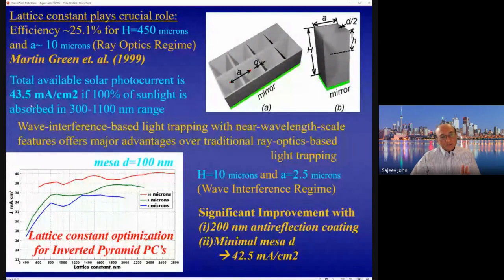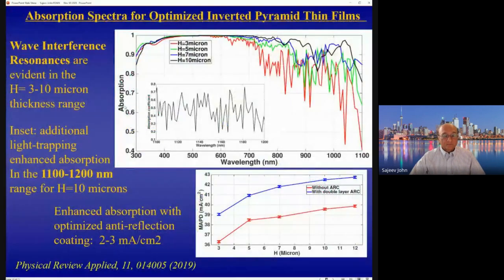And that should be compared with the total available sunlight in the 300 to 1100 nanometer range, which is 43.5 milliamps per square centimeter. And we find that a further improvement is possible if one adds an anti-reflection coating on top of this, say silicon dioxide, and one makes the mesa, this parameter d, as small as possible, maybe as little as near 0. This increases that photocurrent density up to 42.5 milliamps. So with this very thin structure of only 10 microns in thickness, we can absorb about 98% of the sunlight within this broad range of wavelengths, despite the very weak intrinsic absorption of silicon.